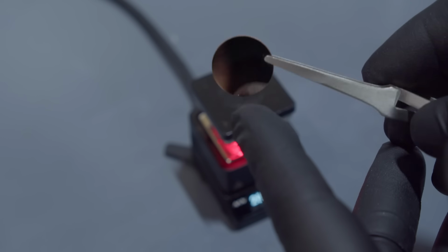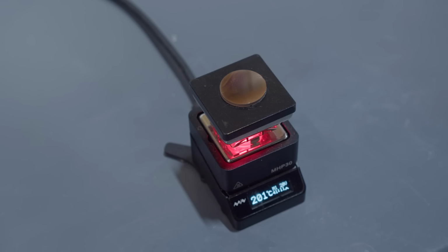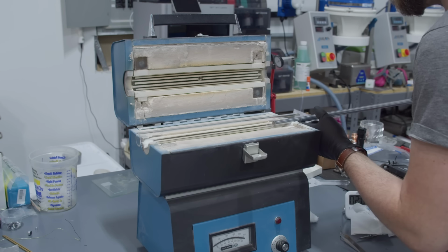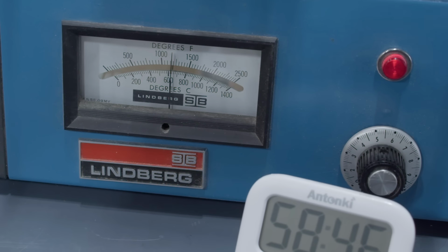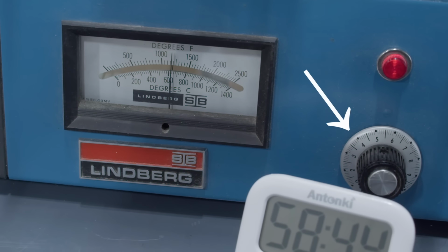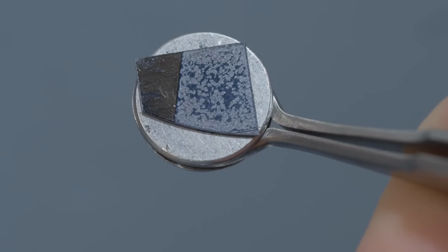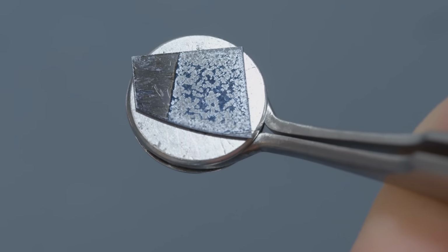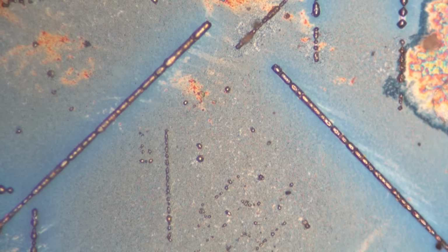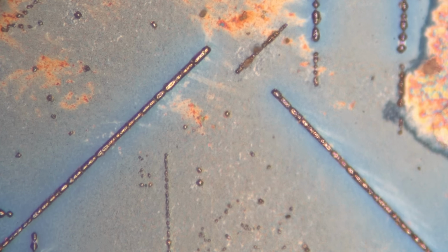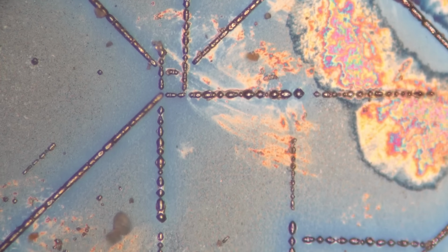If you heat copper up to around 200 degrees Celsius, you'll mostly generate that copper 1 oxide. But as the temperature increases, you'll convert that copper 1 into copper 2. So we put our sample inside the furnace and crank it up to 700 degrees Celsius and leave it there for an hour, which is where the first problem started to happen. My tube furnace just has an analog control method, and if you're not careful, the temperature can kind of fluctuate and swing. If the temp swings a bit too high, the oxide has a tendency to ball up and form these geometric patterns. It's actually really beautiful to look at, but it's entirely useless.